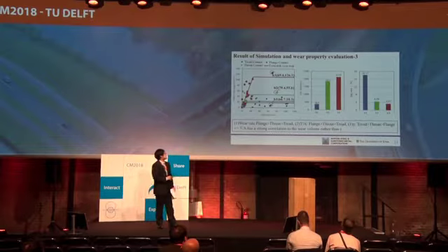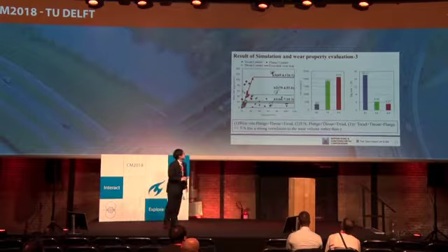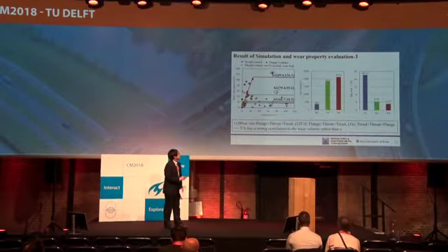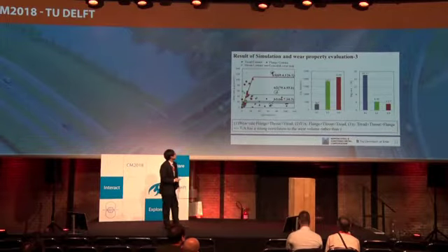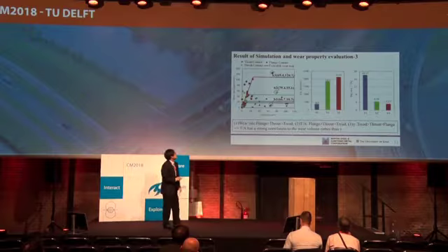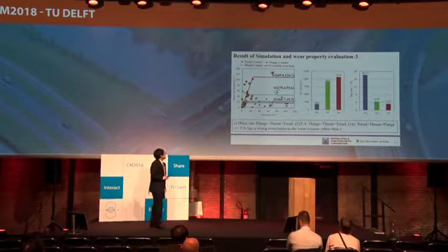From this result, T by A at the flange is larger than at the tread, even at the same T gamma by A. So T by A has a very strong correlation to the wear volume, rather than gamma.